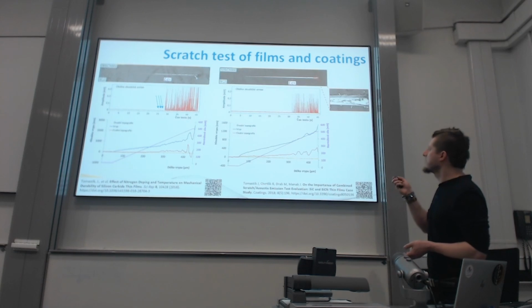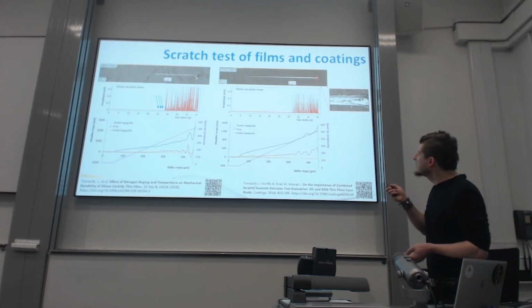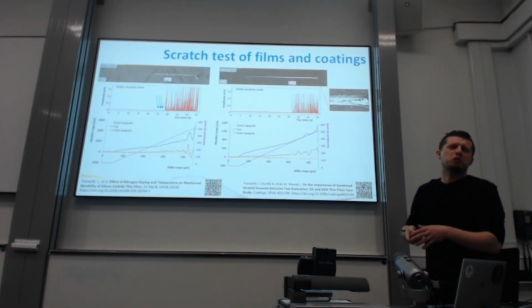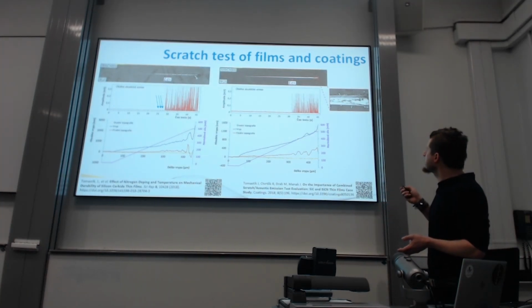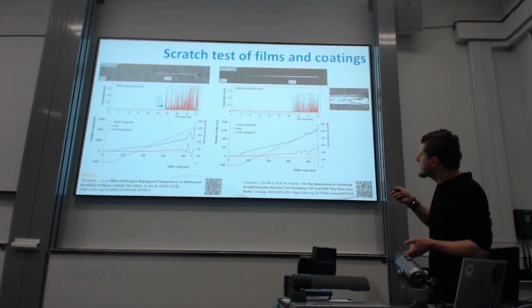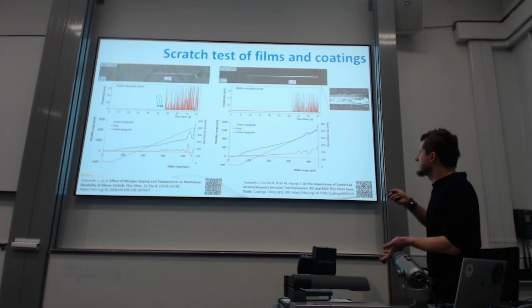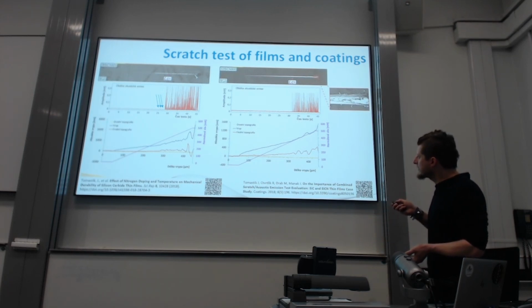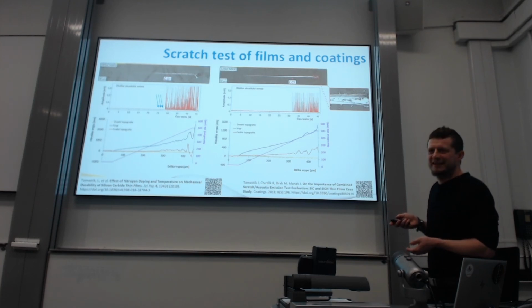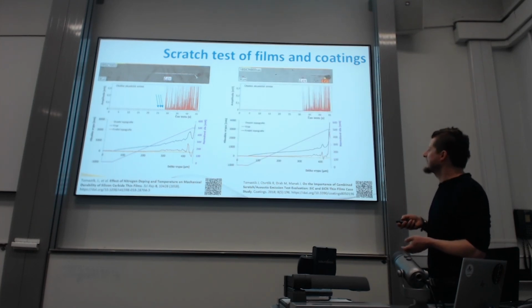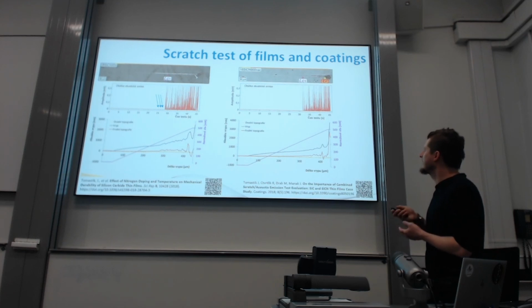There are several more of these scratch tracks, like this one, again a little more tricky. Nothing happening here, so from visual observation, no data. The only cracking visible on the surface was here at the end. Acoustic emission nicely detects this cracking. From the depth change record, maybe if you were bold enough, you would say I can see it, because there is a change of the slope. It correlates, but you need to be bold to say this. But I tried to find something more difficult.